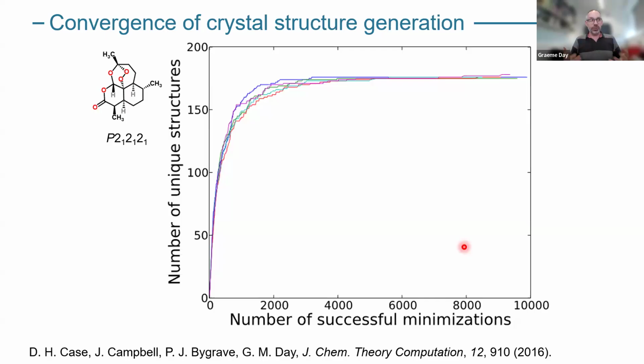To give a little bit of an idea of the number of structures we end up generating when we look for all the structures for a given molecule, here's an example. Here's artemisinin. It's a natural product. Just searching in a single space group, what I'm showing here are the number of structures I've generated in this low discrepancy approach, and then energy minimized. On the vertical axis, I'm showing the number of unique structures. As I go along, I'm finding which of those structures after energy minimization is already in my database and which of them are duplicates of something I've already found. And you see that this increases steeply initially and then starts to tail off.